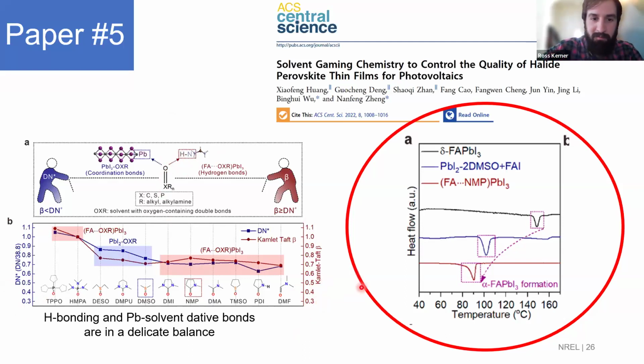And the really nice part of what they've shown is that the solvent can drastically change the thermodynamics to convert to perovskite. And that's an advantage of using solvent processing, among others. But in my mind, this chemically modifying the transition barriers or the temperatures you need to convert to perovskite is huge. And some other processes don't really take leverage of that.